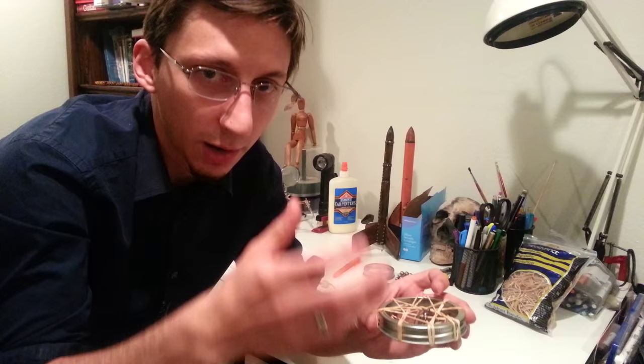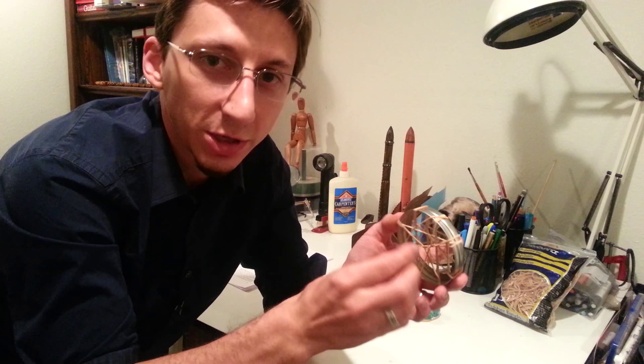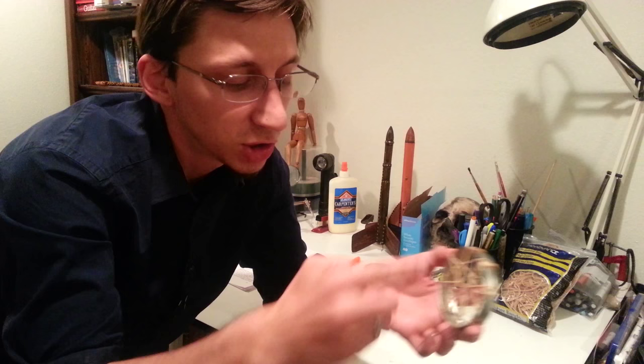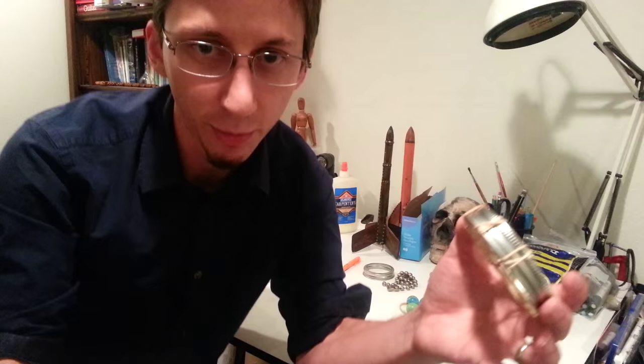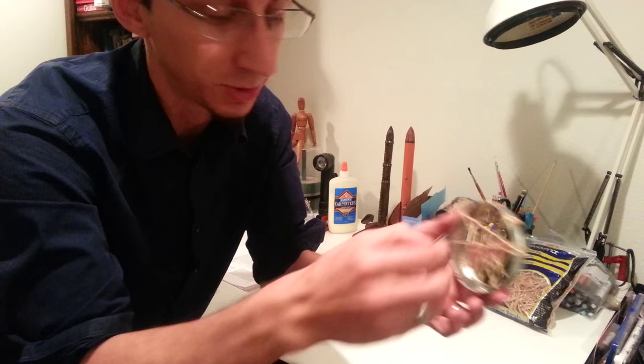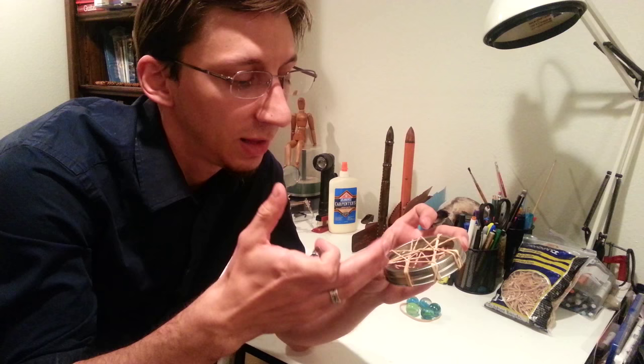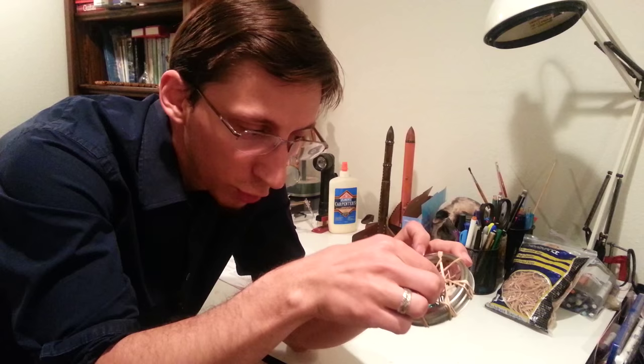But then, when it reaches the other side, the gradient of partial pressure, that means the amount of carbon dioxide in the air compared to the amount of carbon dioxide that's in the latex, is so huge that it just falls out the other side. When we talk about permeability, there's three different processes going on: adsorption, diffusion through the material, and then desorption, where it flies off the other side. The main driving factor for these latex balloons and the carbon dioxide is adsorption and the diffusion through the polymer.